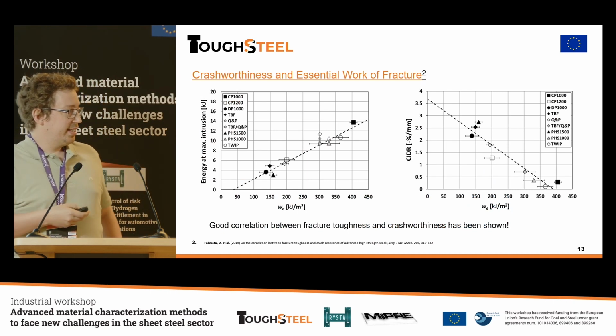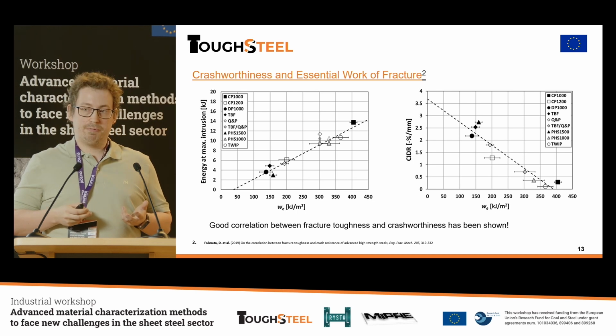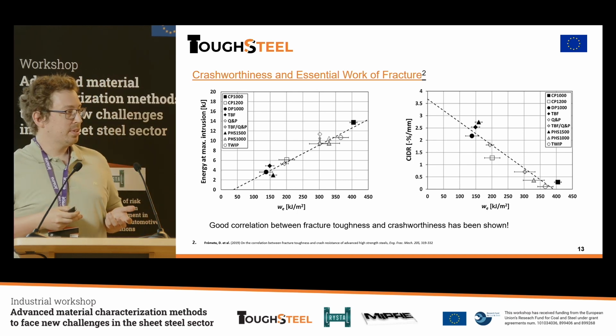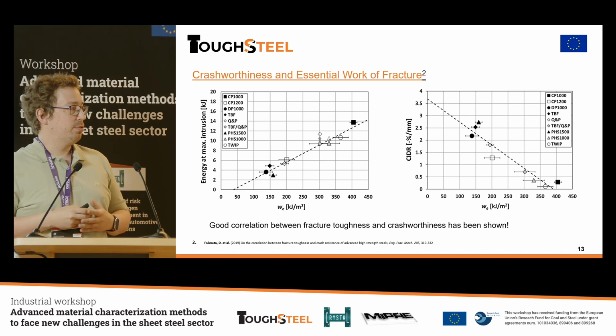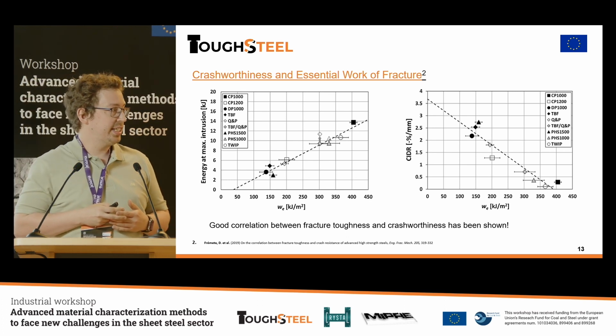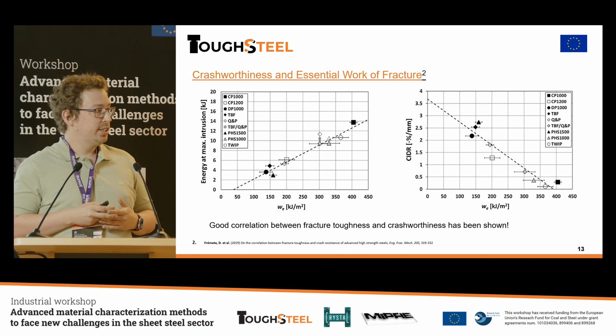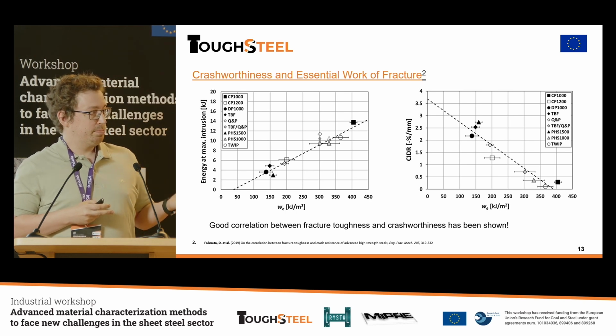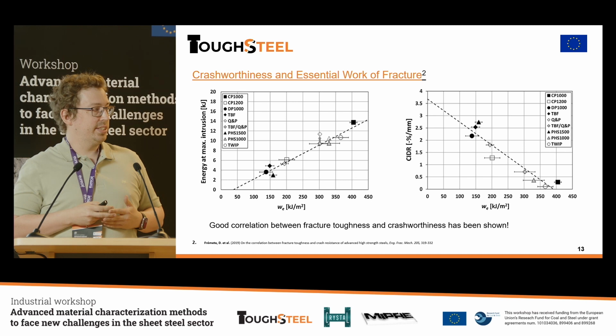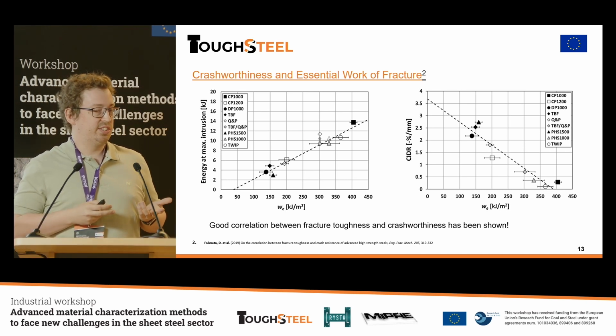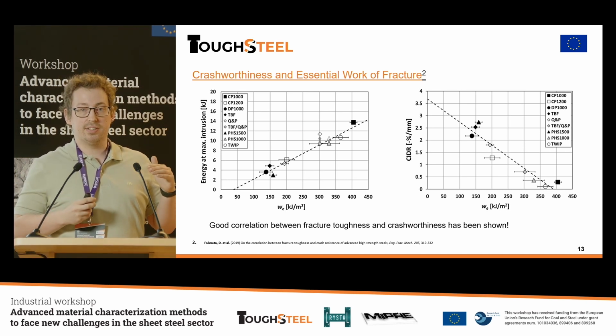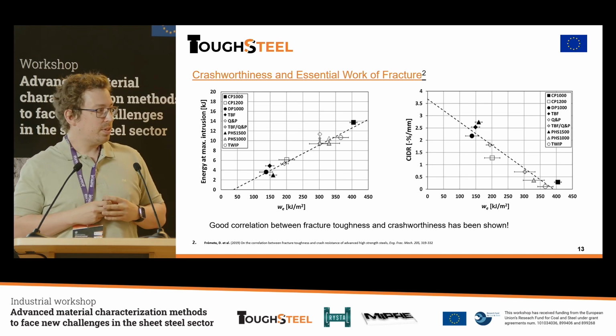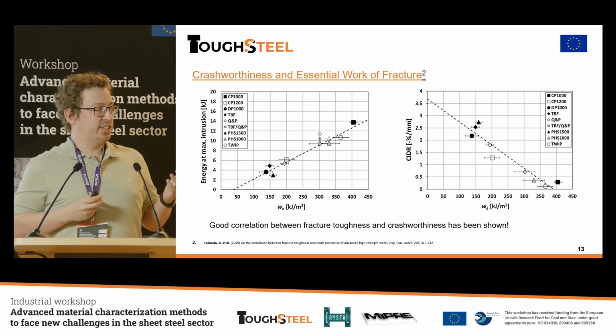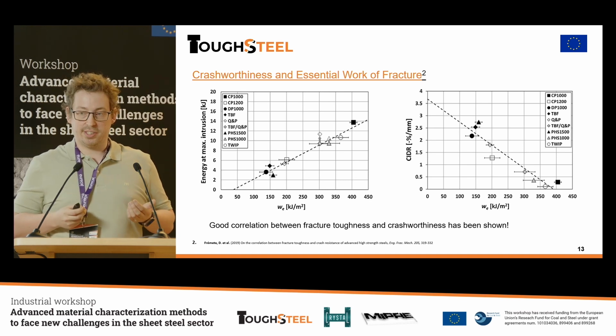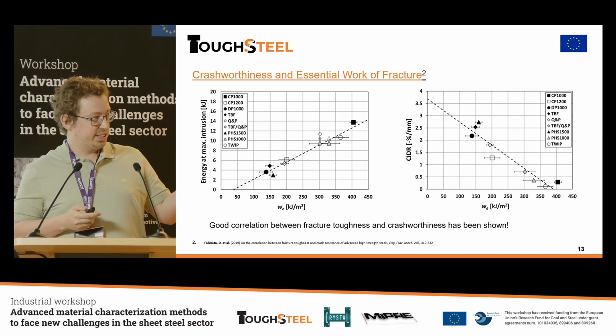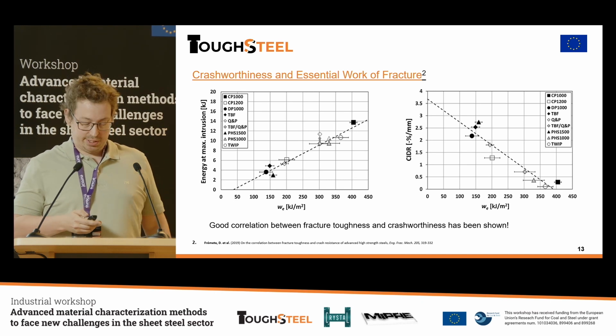Interestingly, Frómeta found a good correlation between fracture toughness measured with essential work of fracture and the crashworthiness of crash boxes. As you can see here, the higher the essential work of fracture, the better the energy absorption at max intrusion, and the better the crash index decreasing rate. It's basically the evolution of the crash index with the intrusion depth. So the lower the crash index decreasing rate, the better the crash resistance. So with a higher essential work of fracture, you get better crash resistance.